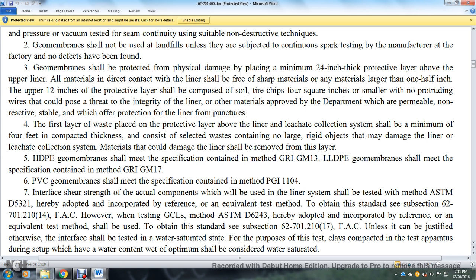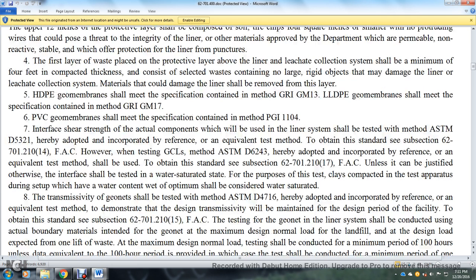Interface shear strength, for the actual components to be used for the liner system, shall be tested by the method of ASTM D5321, hereby adopted and incorporated by reference, or an equivalent test method, to obtain the standard, subsection 62701 21014. Florida Administrative Code. When testing the GCL, the method of ASTM D6243 is adopted and incorporated by reference, or an equivalent test method should be used, to obtain the standard, subsection 62701 21017. Florida Administrative Code. Unless it can be justified otherwise, the interface shall be tested in a water saturated state. For the purpose of this test, clay compacted in the test apparatus during setup at wet of optimum water content shall be considered water saturated.